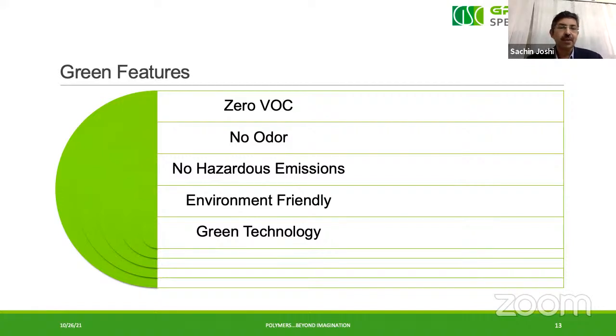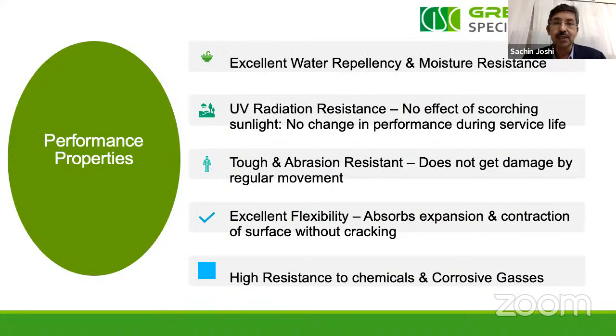The second circle is enhanced performance. Now, because of grafted copolymer technology, we almost have all the properties. Excellent water repellency and the lowest water vapor permeability. Just 5 grams per square meter in 24 hours, where all other systems are 29 grams per square meter per 24 hours. This is a very, very important property, that water vapor will not permeate through or penetrate the polymer film. And that is the reason it behaves successfully, because moisture is the key component which will deteriorate the surface, whether it is metal or concrete or wood or plastics. So it has excellent water repellency and very low water vapor penetration.